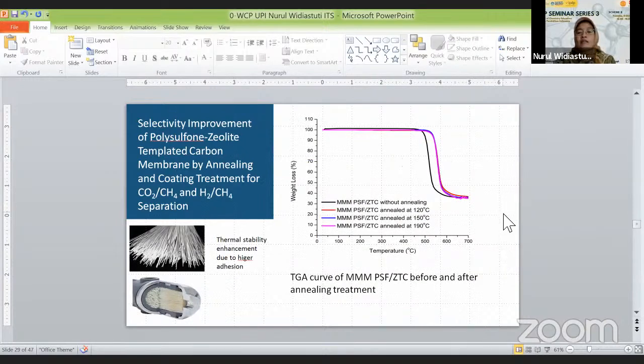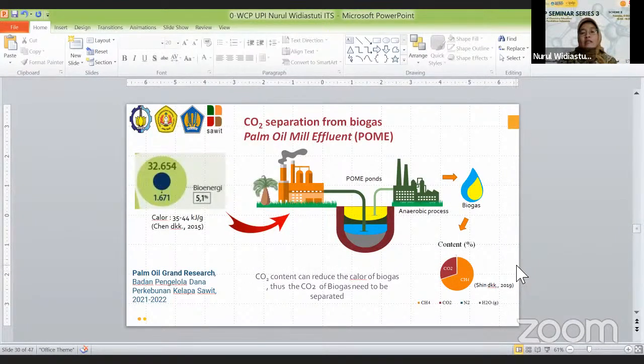And this is the TGA curve of mixed matrix membranes before and after the annealing process. As we see here, the effect of annealing can make thermal stability enhancements due to the higher adhesion. And at the moment we are conducting research using these kinds of materials, some of them as I presented here, and we apply these materials in CO2 separation from biogas of palm oil mill effluent.